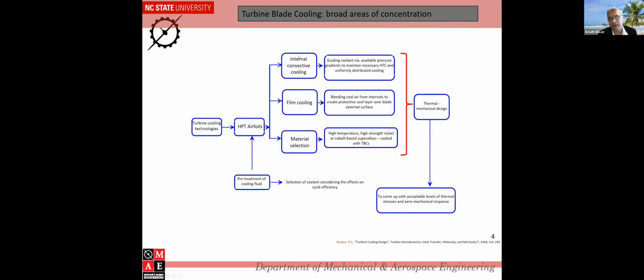Then you have the internal convective cooling, which is basically guiding the cooling through the holes to the channels inside the blade and making sure that it enhances the heat transfer. Then you got the film cooling, which is coming out of the holes. That's going to provide the cooling coating along the surface. And then you have the materials selection, which is choosing the right amount of material so it can sustain it.